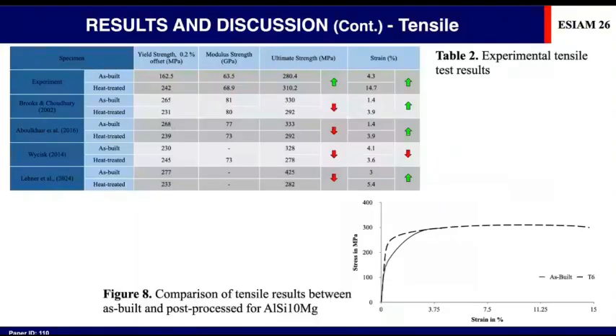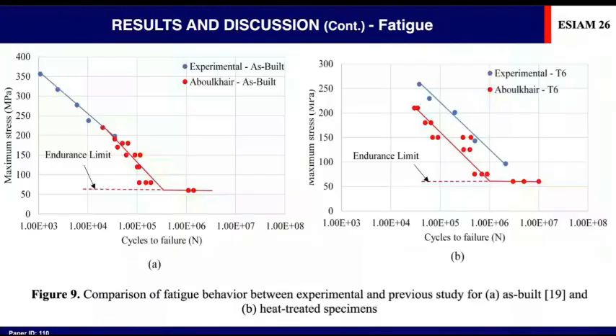Based on the experimental tensile test results, heat treatment increased the UTS and the strain performance. Meanwhile, most of the literature shows the UTS decreased but the strain performance increased after heat treatment. However, another study shows a reduction in both UTS and strain after the T6 heat treatment. For the fatigue behavior, the fatigue life result is better compared to the previous study. One of the reasons is that the author performed the solution heat treatment for T6 in a different way in terms of duration.